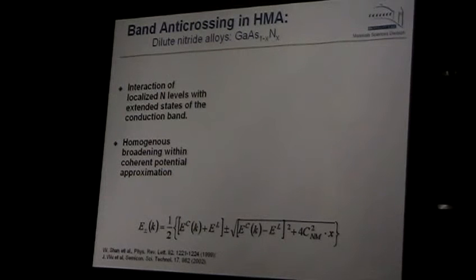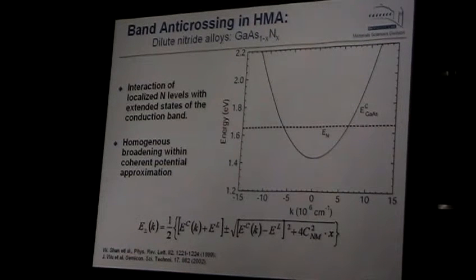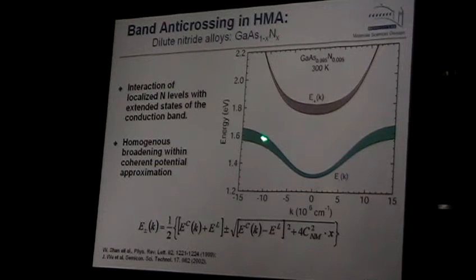So at some point we thought about this, and we knew that when you introduce nitrogen in a material, so this is the gallium arsenide conduction band, this is a parabolic conduction band. We knew that nitrogen introduces a localized level. So this is this line here. If you put more nitrogen in, if you start to alloy it, the original states of the gallium arsenide interact with these nitrogen levels, and the band is split into two parts. This is the so-called band anti-crossing.